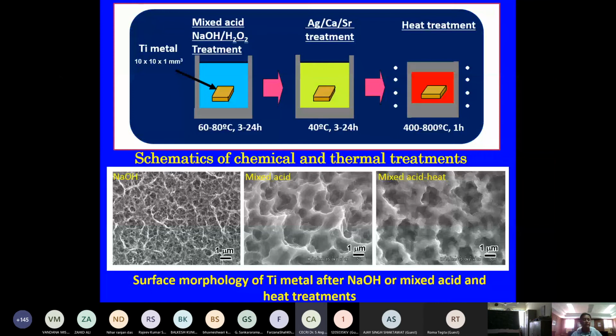And instead of sodium hydroxide or hydrogen peroxide, if you treat with some strong acid, you can see micro pits forming on the surface, so this is basically modifying the surface to micro pits. So we used to play with different types of chemical treatment and modify the surface, and we try to compare which type of surface has better bone integration, biocompatibility or bioactivity.